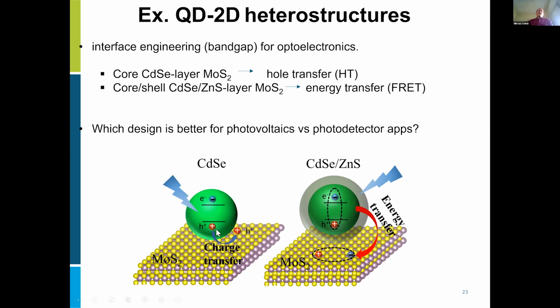So we used core quantum dots. The energetics of the core quantum dot in this particular case with the 2D material, which is molybdenum disulfide, allows a hole to move from the photoexcited quantum dot into the 2D material. While for the core-shell, because we have this high band gap material, we can only transfer the whole pair, the electron bound to the hole, which we call an exciton, into the second material.